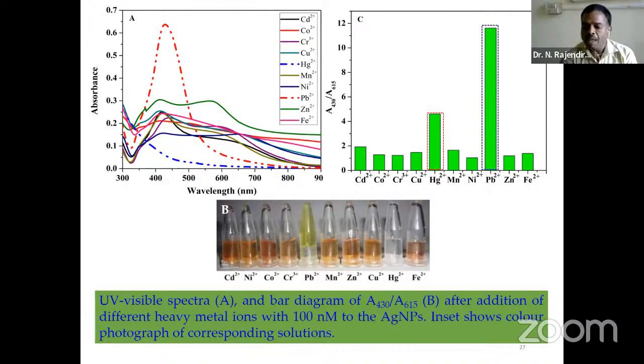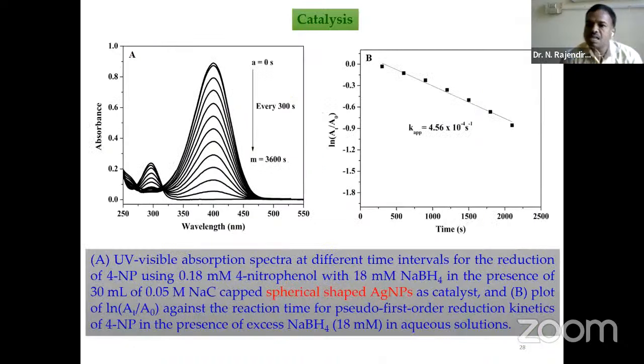If you add toxic or heavy metal ions, what will happen? Here we have only two different ions interacting with the metal nanoparticles, compared to other metal ions, so we can use it as a selective colorimetric probe for detection. Colorimetrically, we can detect the metal ions in environmental samples at the nanomolar level. And these metal nanoparticles are also very good catalysts.